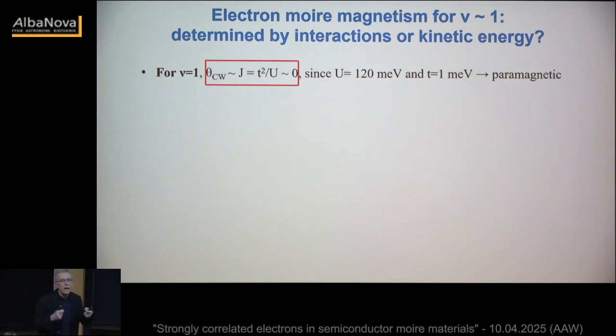So for nu equals 1, the standard expectation, and actually that was ours, was that the system should form a 120-degree anti-ferromagnetic Néel state. Right? That's what you would read in textbooks. But if you do the numbers here, the super exchange interaction is almost 0 because U is so large. Right? So for the temperature ranges that we are measuring, which is down to 150 millikelvin, there is no way we will see any deviation from paramagnetism. So in that sense, even if there are some anti-ferromagnetic correlations, we cannot say.